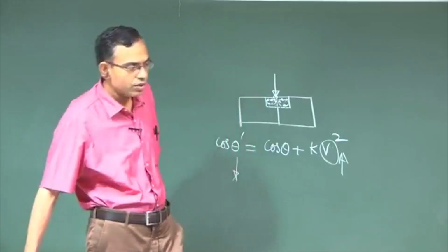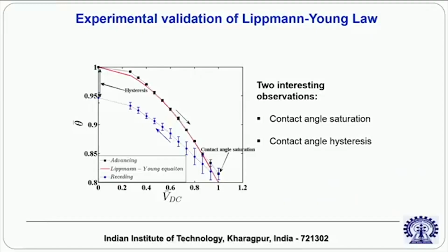So, this phenomenon is known as contact angle saturation. If you look into this theta versus voltage, this V DC stands for a DC voltage. You will see that it will come to a saturation with increase in voltage, and then it does not change anymore. So, this is one interesting phenomenon. The other phenomenon is that if you reverse the bias, reverse the voltage, you will see that the way in which the contact angle got decreased is not the same way in which the contact angle got increased. So, there is a hysteresis.